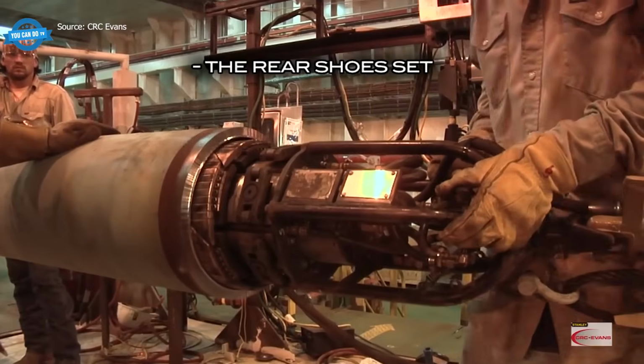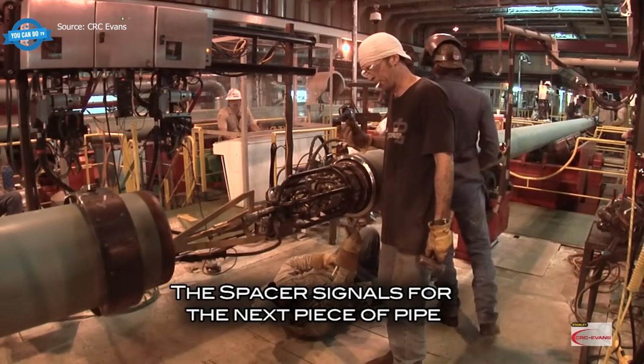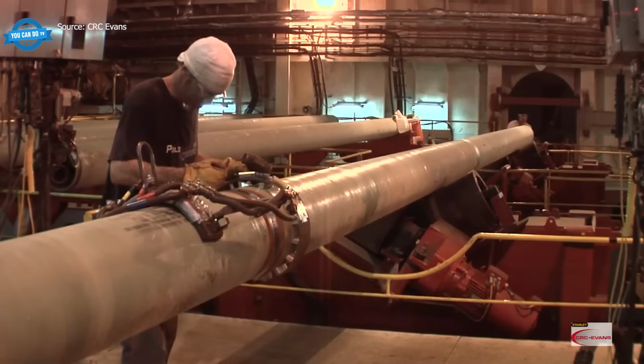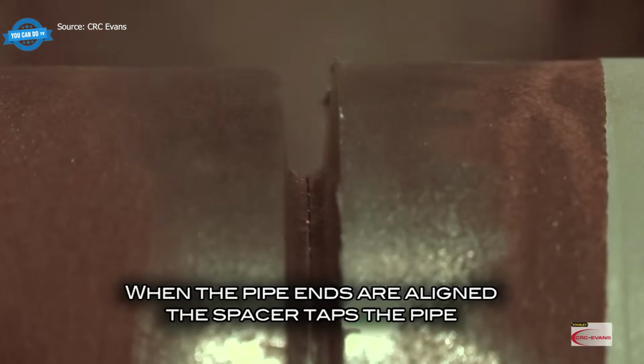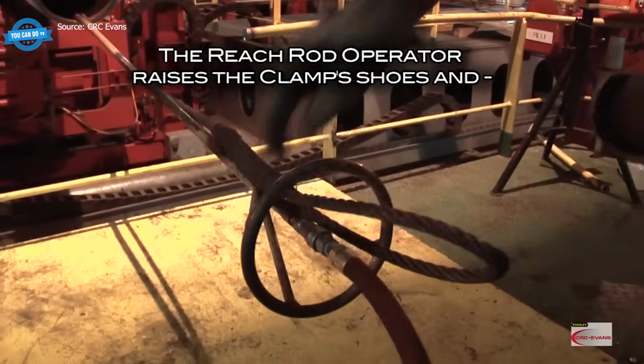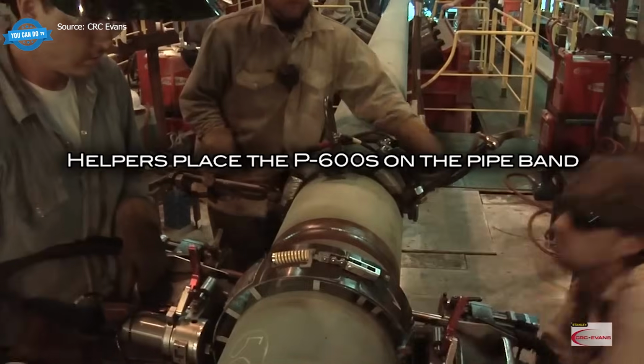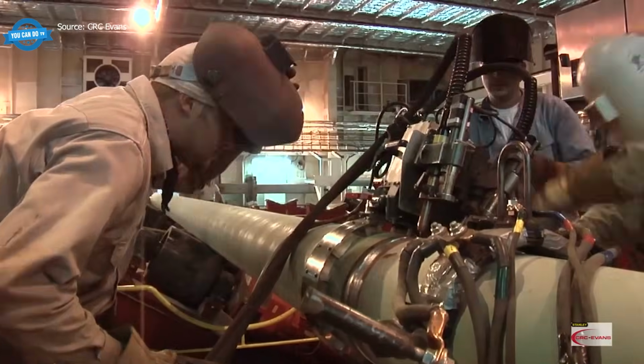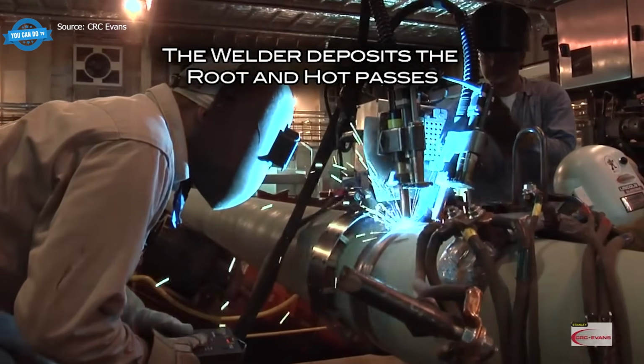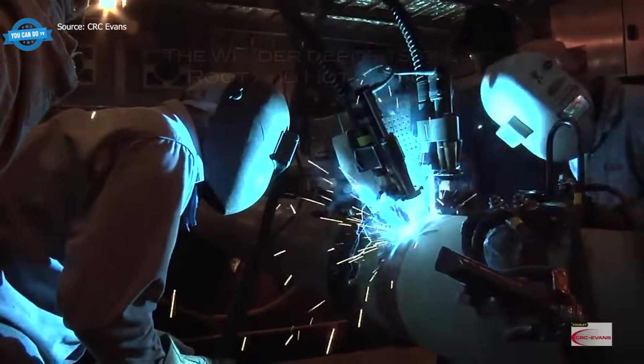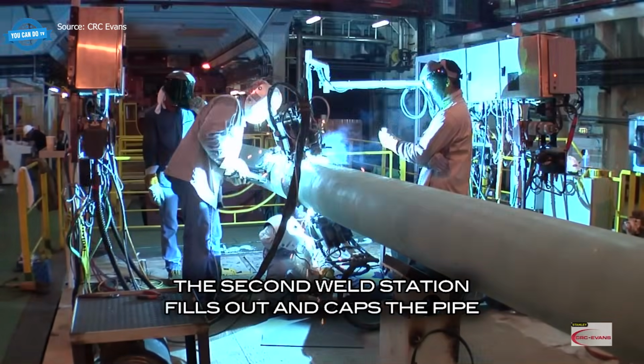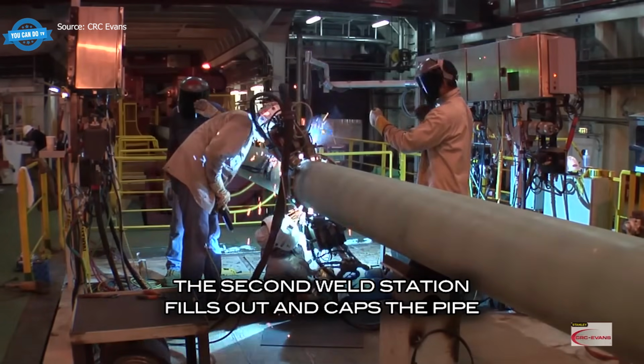The pipe then moves into the preheat area where induction torch bands heat the steel and drive off any surface moisture that would otherwise spoil the weld. At the welding station, the next pipe is aligned to the existing pipeline string using a reach rod and an internal pneumatic clamp that locks the joint rigidly from inside. Automatic welder heads then begin work. The first head lays down the root pass. The next station lays down the hot pass, subsequent stations add fill passes, and finally a cap pass that closes the joint.